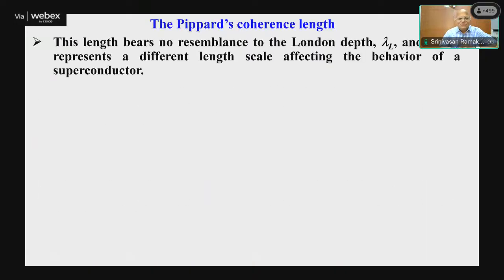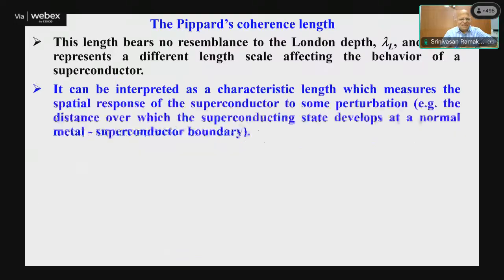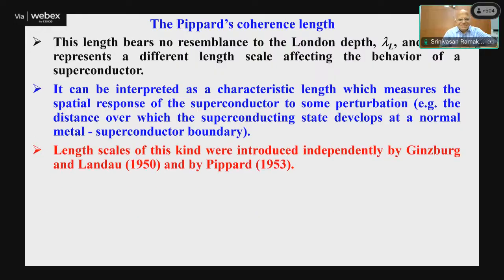So once he introduced that, this length bears no resemblance to the London penetration depth, hence represents a different length scale affecting the behavior of a superconductor. It can be interpreted as a characteristic length which measures the spatial response of a superconductor to some perturbation. So it is the distance over which the superconducting state develops at normal superconductor boundaries. A length scale of this kind was introduced independently. We will see that the Ginzburg and Landau theory also introduces these things, which is closely related to Pippard's.